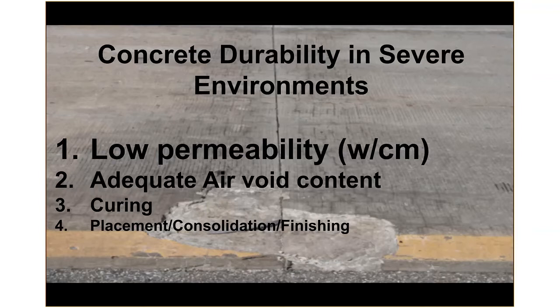Now, when concrete does not have low permeability, you get salts, brines, things that go into the concrete and allow the concrete to become more critically saturated and hold more water due to osmosis. Fresh water will then get pulled into the concrete, especially at the joints, and with the salt, allow that concrete to become critically saturated. So when the water freezes into the void space, it may be sucking more water in there, and we get things like joint rot, joint distress, freeze-thaw distress, scaling, things like that. And so it's a big deal to keep water out, keep salts out by producing low permeability concrete, allowing that air void system to further protect the concrete.